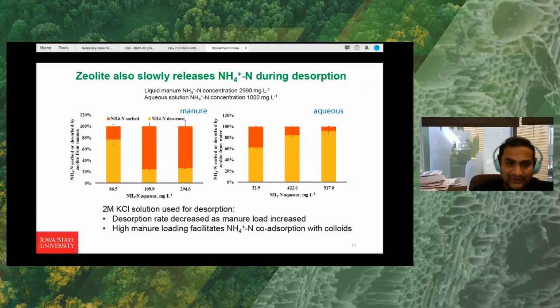So the yellow is the desorption and the orange is the absorption. So the zeolite shows less desorption from the manure than from the aqueous. So here also we can say that the desorption rate decreased as the manure load increased, and also the high manure increases the percentage of colloids, which facilitates the absorption of ammonium. So that means in these two slides we have shown that both biochar and zeolite can absorb ammonium and can slowly release ammonium during the desorption study.